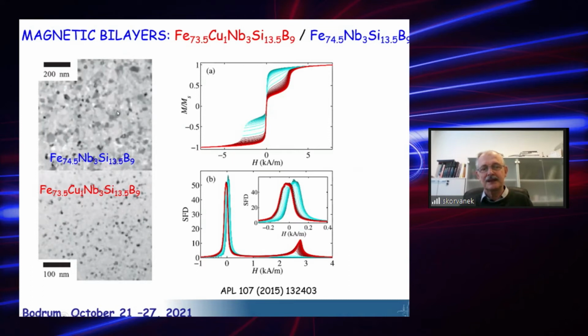to average out magnetocrystalline anisotropy in accordance with the Herzer model, and the coercivity will be higher. So we see that such a two-layer ribbon exhibits kind of two coercivities. One is here, it's fine met, and another one somewhere here. It's this layer with bigger grains. So we have something like soft and hard, or in this case we can call it semi-hard, because it's not really a very hard material.